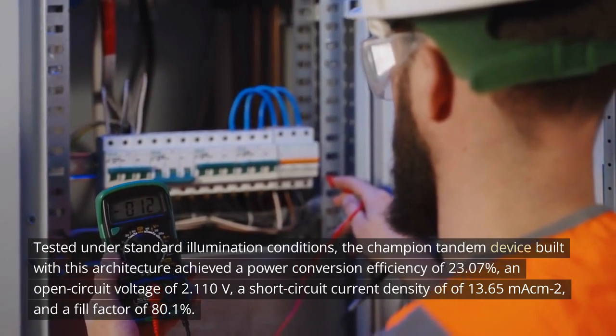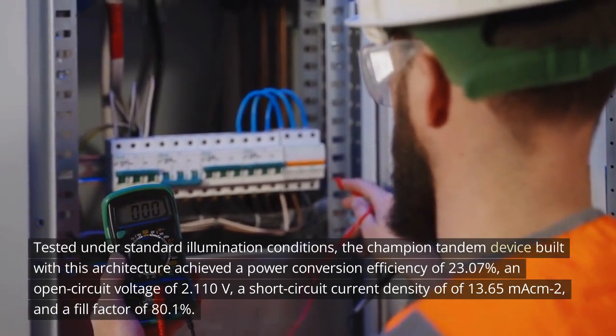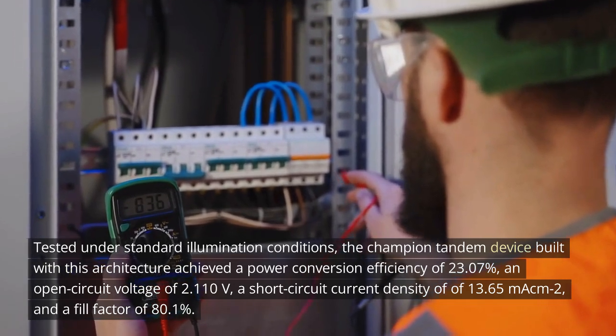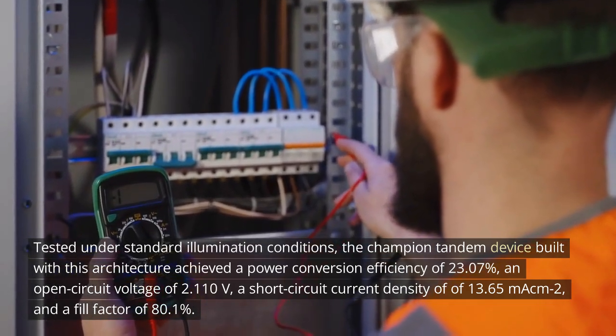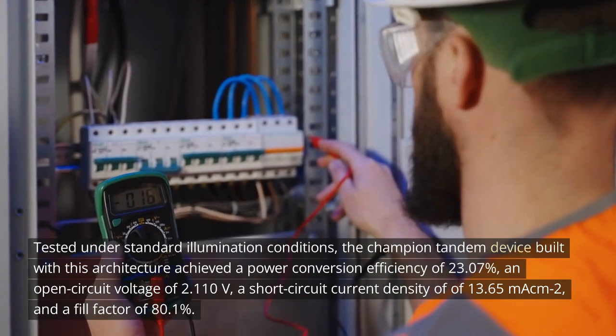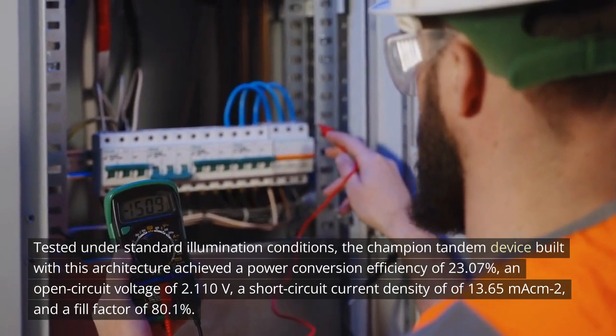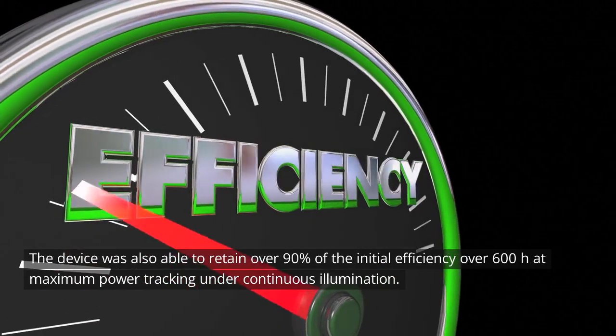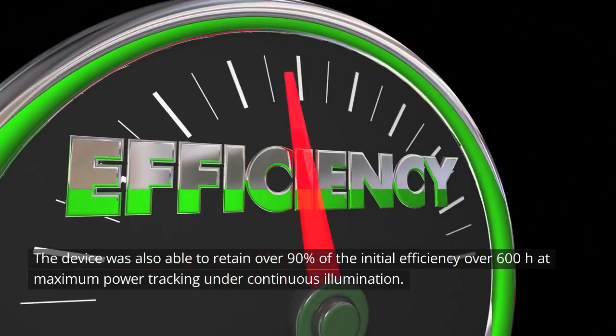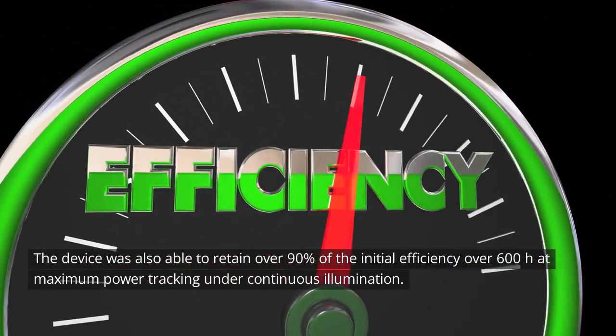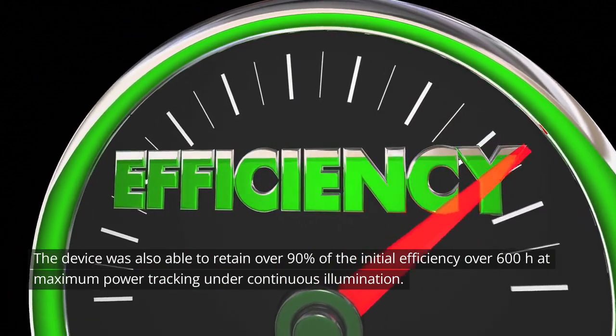Tested under standard illumination conditions, the champion tandem device built with this architecture achieved a power conversion efficiency of 23.07%, an open circuit voltage of 2.110 V, a short circuit current density of 13.65 mA/cm2, and a fill factor of 80.1%. The device was also able to retain over 90% of the initial efficiency over 600 hours at maximum power tracking under continuous illumination.